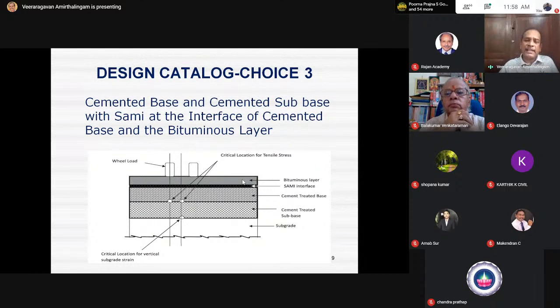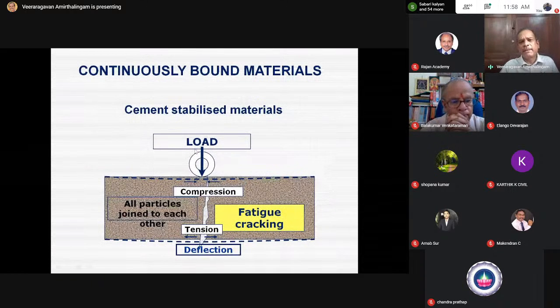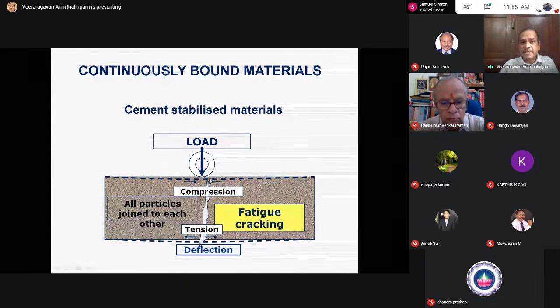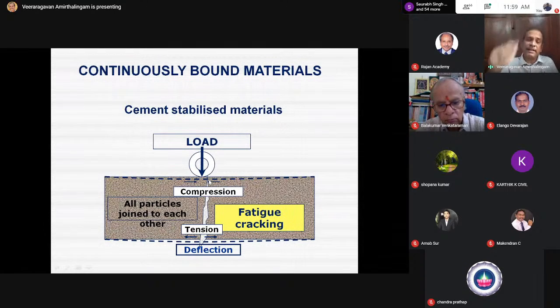In lieu of the granular layer, I have come to the issue of why a granular layer. I go in for a SAMI, stress-absorbing membrane interlayer, which can be a bitumen-impregnated geosynthetic layer. All are crack retarding layers. I don't say crack prevention layers, crack retarding layers. They will prevent the crack from the cement-treated base from propagating to the bituminous layer. So what will happen is that it's a continuously bound material. With a repeated application of load, there will be a tension at the bottom, so there will be a crack that will form. If you don't take care, this crack will propagate.